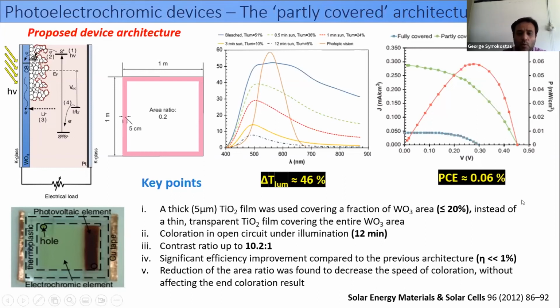and the photoconversion efficiency is still below 1%, but is higher than a device having a transparent titanium film, as we saw here in these JV curves. Our newly proposed device has the JV curve as we show here with a green line, and the blue line is the device with a transparent titanium film. Also, the titanium film covered a fraction of 20% of the total device area.